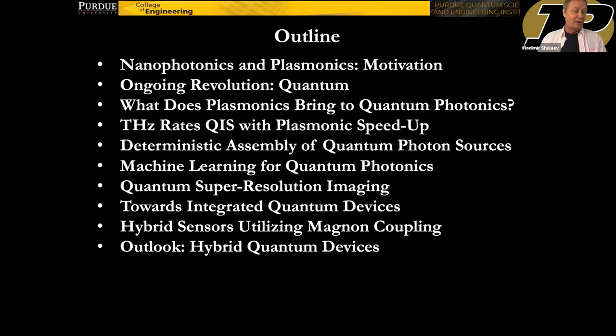because if you use, for example, a transition metal nitride like titanium nitride, it has very similar plasmonic properties, and it seems most compatible as opposed to gold. I'm talking about quantum photonic circuitry. And of course, for this, you need to use the most compatible materials. I told you how important it is to use silicon nitride. Titanium nitride is the most compatible material, and it could sustain very high, elevated temperatures. It means that your plasmonic structure would not deteriorate when you irradiate it with light. But that's not the only plasmonic material.